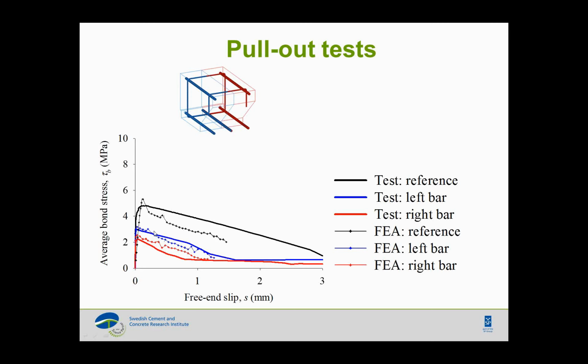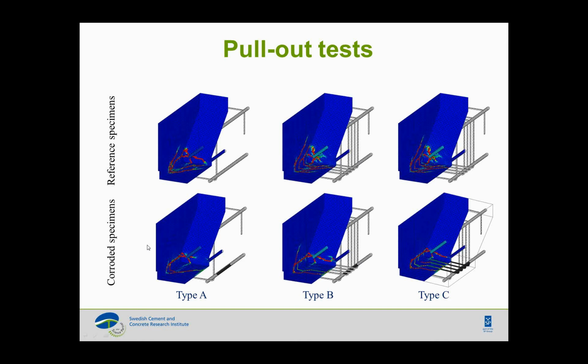Looking at some of the crack patterns coming from simulations. On the top we have reference specimens with no corrosion imposed, and on the bottom we have corroded specimens. And we see that corrosion highly influenced the crack pattern. Here we have more of a corner covers fall. When you pull out the reinforcement down here, we have the corner covers falling, but also the interaction between corner reinforcement and middle reinforcement. And then when we move towards the case where we have stirrups corroding, it's more of a bottom cover delamination case, and that is very well shown in the simulations.